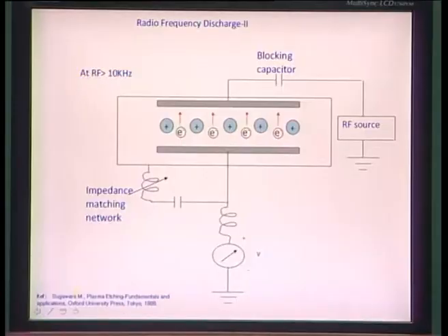and due to which sometimes the plasma plates in such an RF discharge, above a certain frequency above 10 kilohertz, attain a negative charge in comparison to the bulk of the plasma, which is otherwise positive because of the accumulation of the ionic species within the bulk of the plasma.